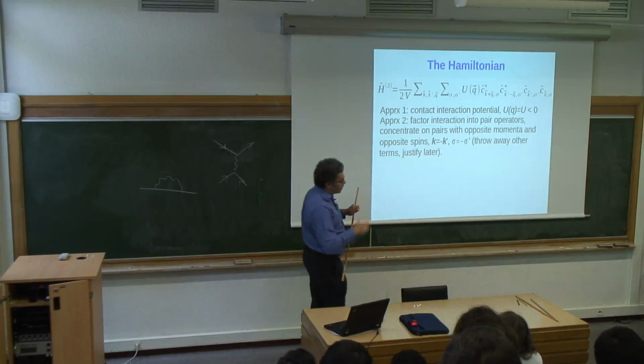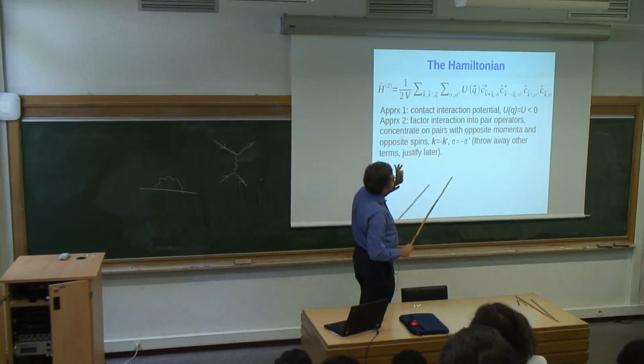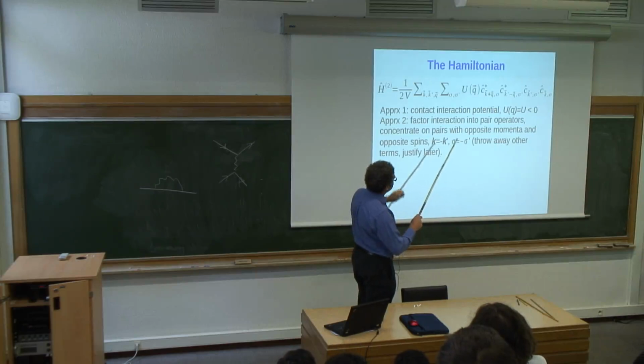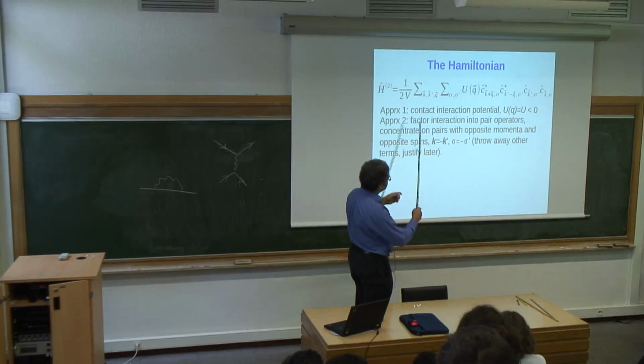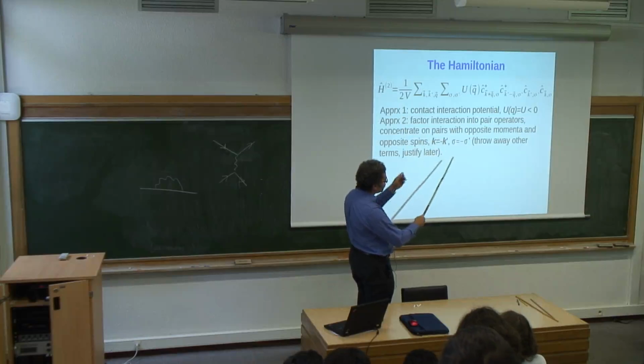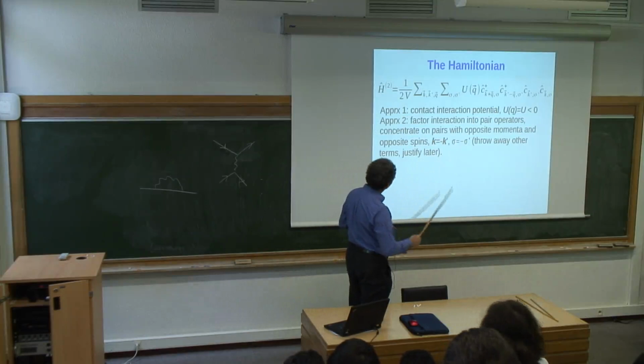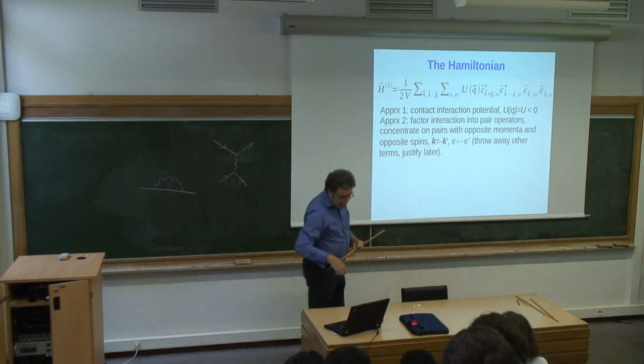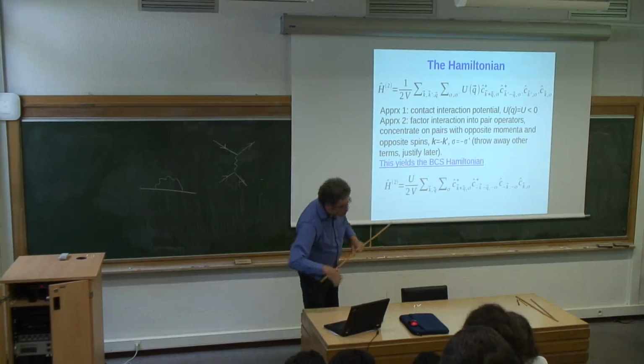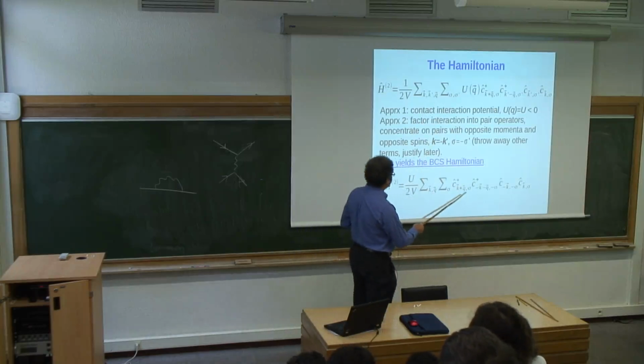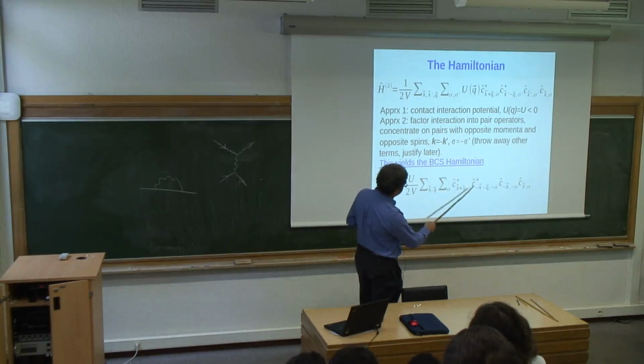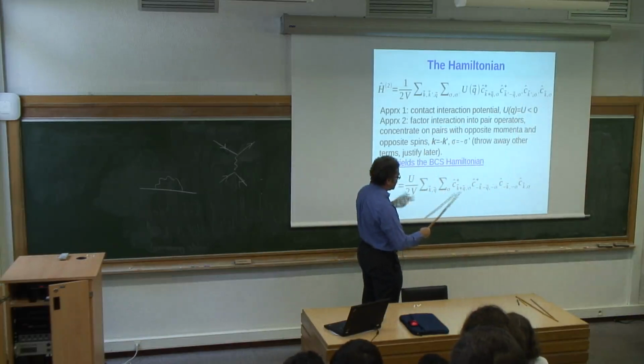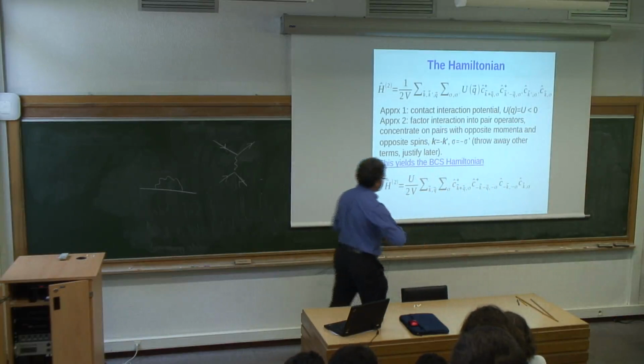But because of that intuition that we have that the particles which are pairing are counter-propagating, it's useful to suppress part of this Hamiltonian and focus on the terms that correspond to incoming particles having opposite momenta, and also, if we're talking about pairing in a singlet channel, opposite spins. One can relax it later. But that's the starting point of the BCS Hamiltonian. So if you do this, then you get a Hamiltonian that looks almost the same, except that I replaced arbitrary incoming momenta by counter-propagating momenta, and arbitrary outgoing momenta also by counter-propagating momenta.